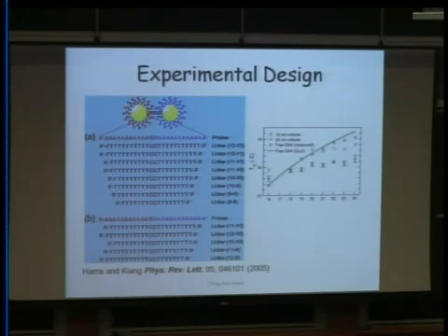So what we found is if the target and the linker bases have a different number, so one is 12 bases, one is 11, that means these two are a little bit different. They'll have a different, lower than expected melting temperature. So in addition, sometimes the free solution DNA thermodynamics, it's not necessarily so directly you can just apply that to the surface DNA reactions.